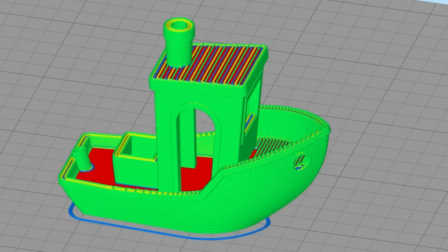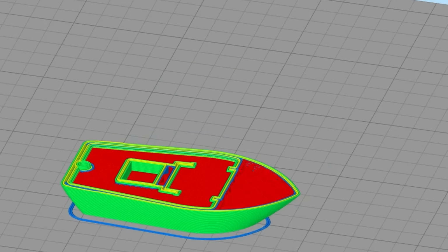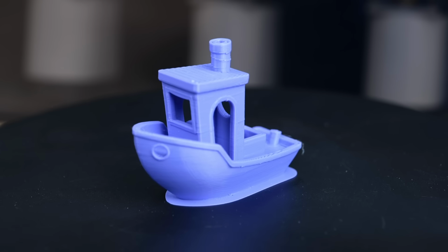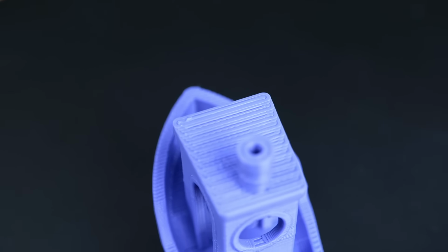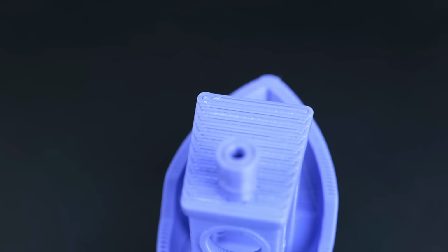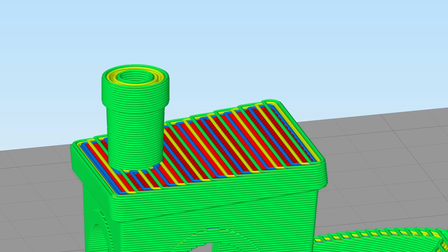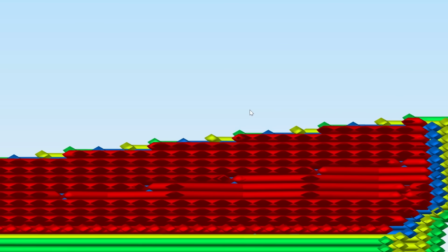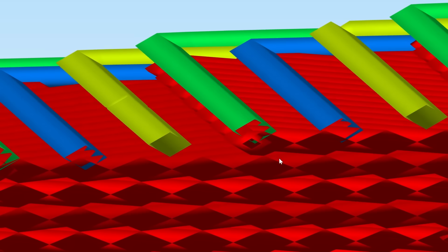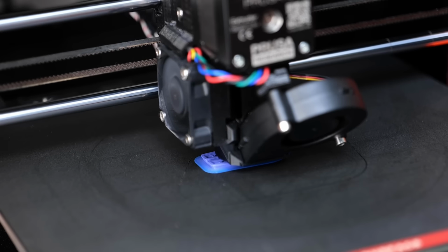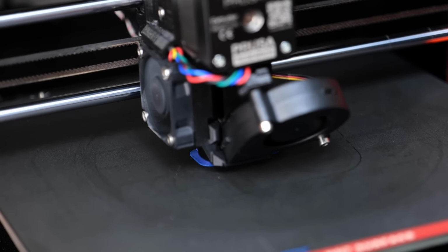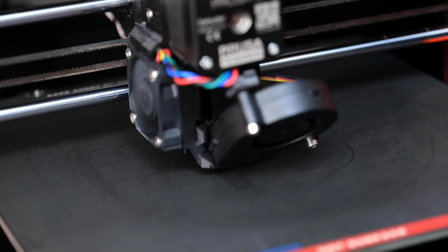Also, more complex parts like a 3D Benchy look good in the slicer and print similarly well on a real machine. Outer surfaces look way better than I expected, and only sloped top surfaces seem to be a bit under-extruded. The reason for this is that the slicer misses some of the intermediate layers due to the shift in slicing height. Yet this might simply be fixed by printing layers at half the height once the top of a part is breached. This is nothing I can probably implement in my proof of concept, and would be something that needs to be looked at in a proper slicer implementation.